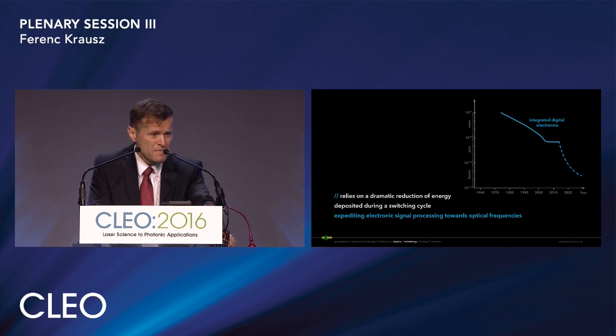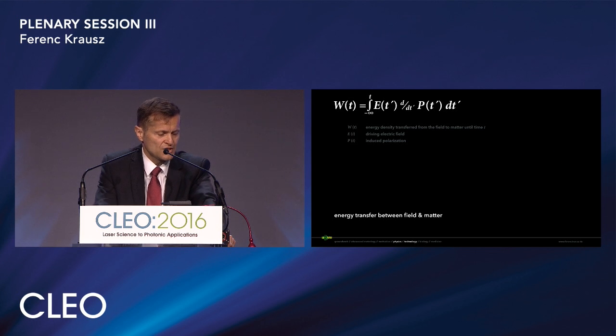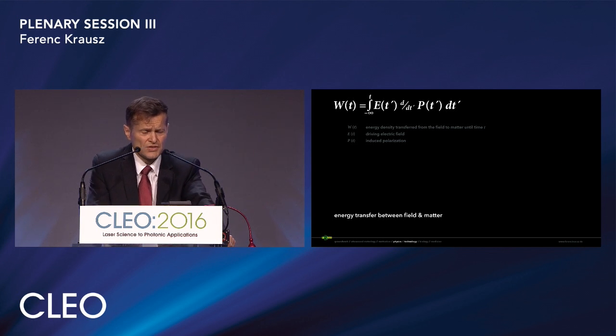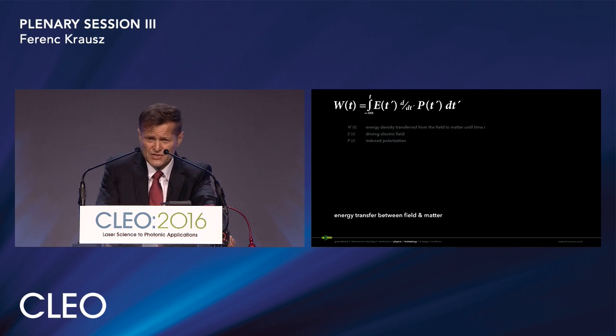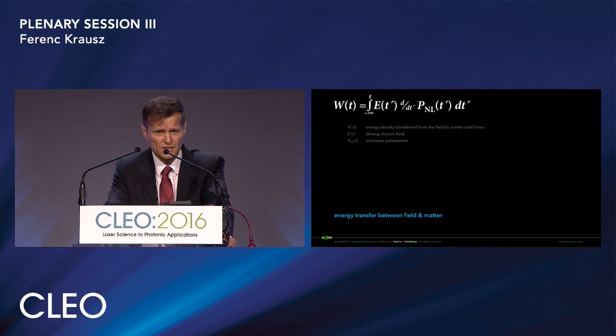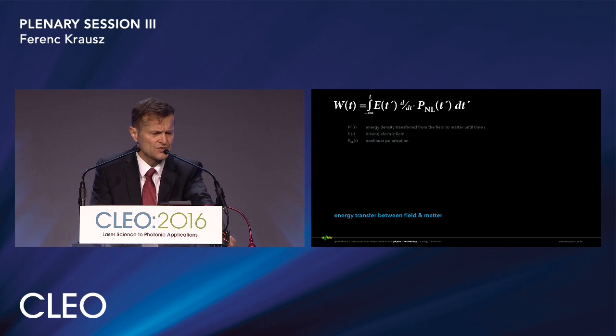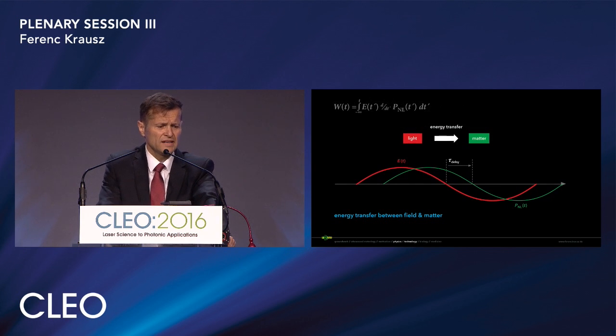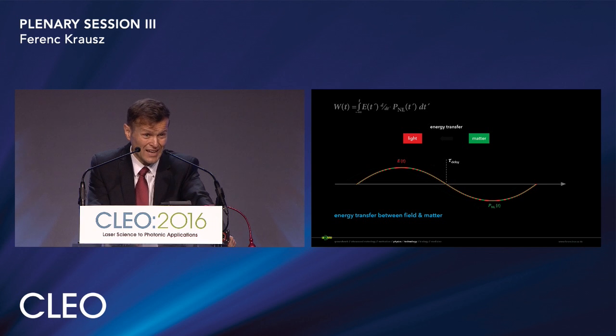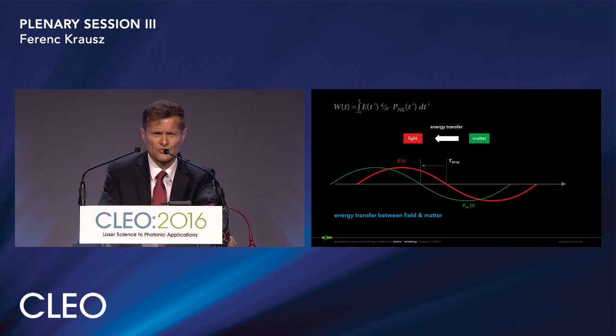This would rely on a dramatic reduction of energy deposited during a switching cycle, which of course requires insight into the energy transfer between optical field and matter, described by this simple integral. In wide gap systems, the linear polarization oscillates perfectly in phase with the driving electric field, zeroing the net cycle averaged energy transfer. A net energy flow then depends on a nonlinear polarization that can possibly be induced at increased field strength. The direction and the magnitude of the energy flow then depends on the timing, on the precise attosecond timing of this nonlinear polarization with respect to the driving field.